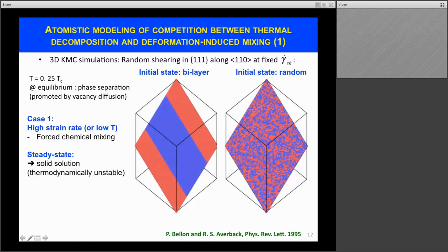And in this system, we're going to work in a region of the phase diagram where at equilibrium it would phase separate. And this phase separation in the simulation is promoted by vacancy diffusion. And what we're going to do is, on top of this thermal diffusion, superimpose shearing as it would result from the glide of dislocations through this material.